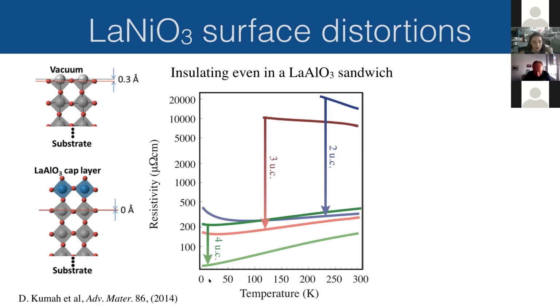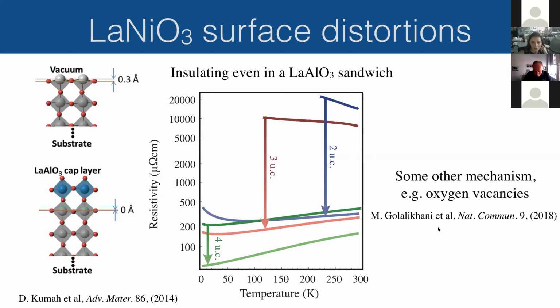So here is, again, my data. If you go from a 4 unit cell sample without a cap to with a cap, of course, you have a decreased resistivity. It's much better because the nickel-oxygen-nickel bond is not so bent. With 3 unit cells, you have an even bigger effect. With 2 unit cells, an even bigger effect than that. But still, you start to see at 2 unit cells that this is becoming insulating at low temperature, even if it's in a sandwich of lanthanum aluminate. So this is not the full story. This explains a bit, but not everything. And maybe, as some people suggest, there could be other mechanisms in the end for 1 unit cell of lanthanum nickelate, such as oxygen vacancies that are making it insulating.